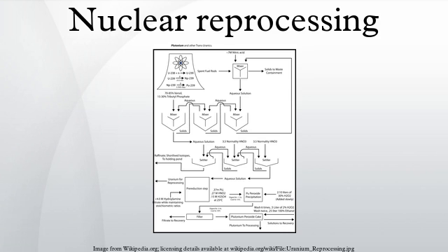In contrast, the PUREX process was designed to separate plutonium only for weapons, and it also leaves the minor actinides behind, producing waste with more long-lived radioactivity. Most of the radioactivity in roughly 10² to 10⁵ years after the use of the nuclear fuel is produced by the actinides, since there are no fission products with half-lives in this range. These actinides can fuel fast reactors, so extracting and reusing them reduces the long-term radioactivity of the wastes.